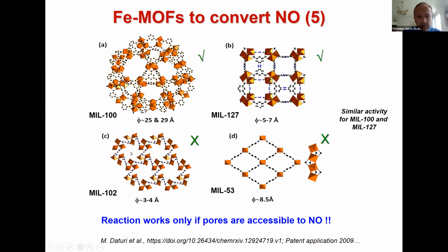can also be reduced, but then in this case, the activity is almost negligible, probably because you don't have sufficient accessibility for the catalytic reaction inside the pores. And of course, if we use MIL-53 that has no metal site and it's pure iron 3, there's no activity at all. This means that the reaction needs this reducible trimer, but also a certain pore size to have the reaction.